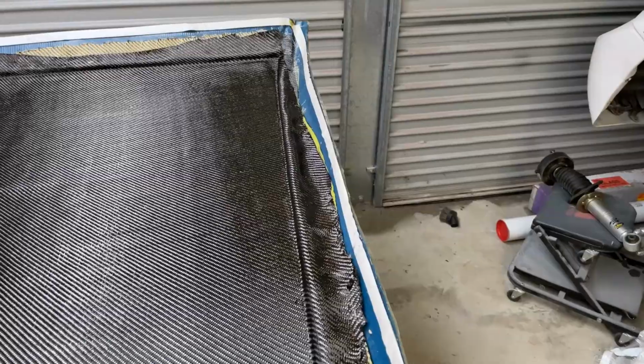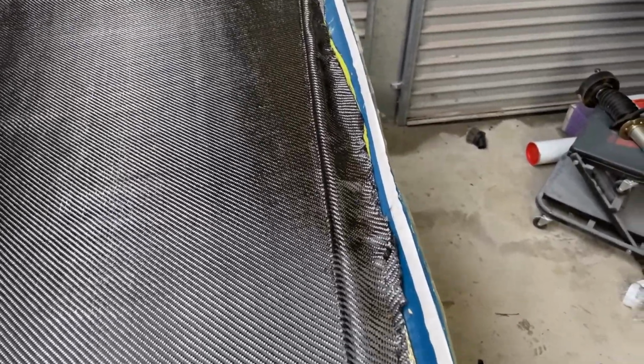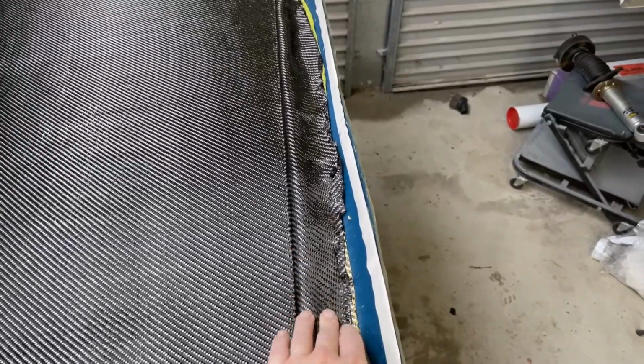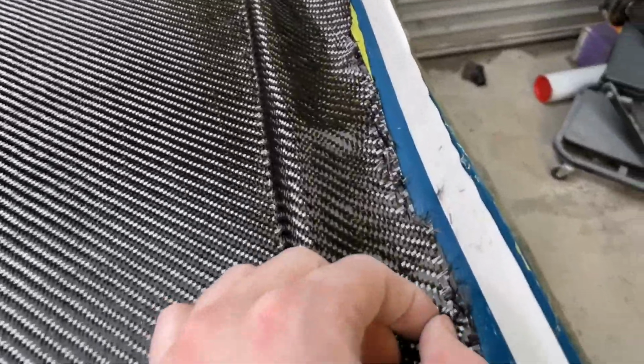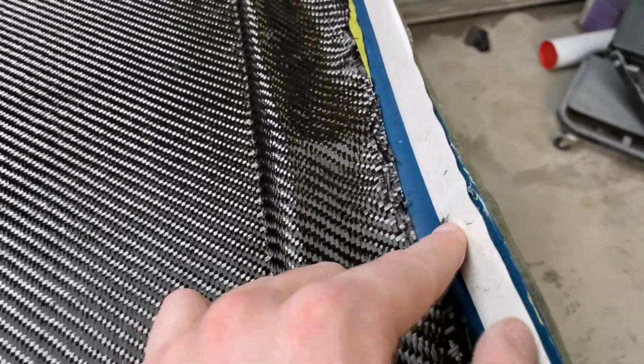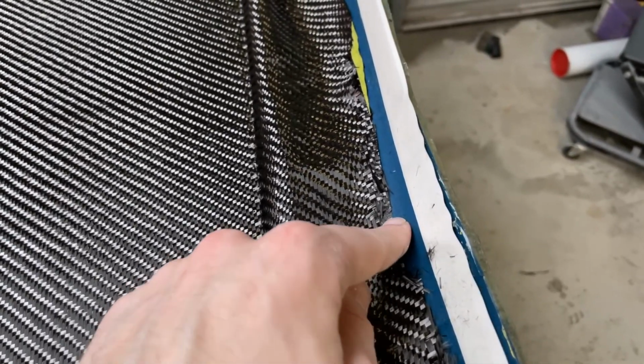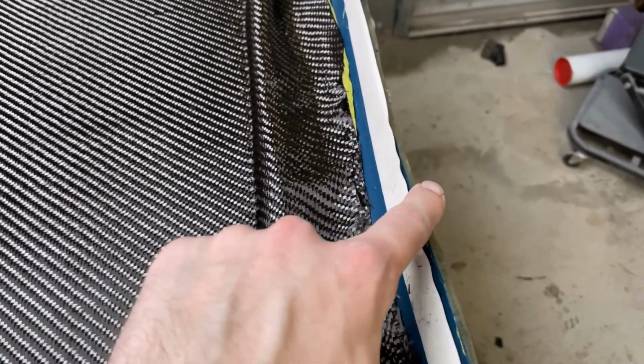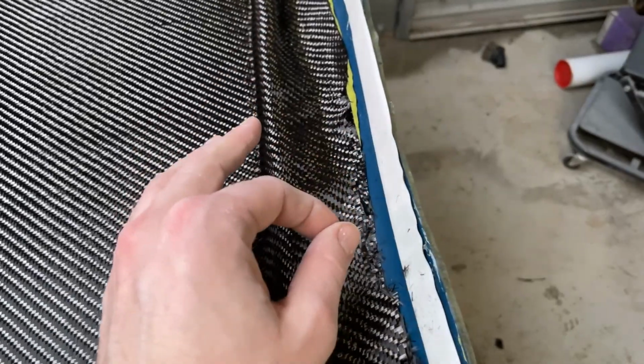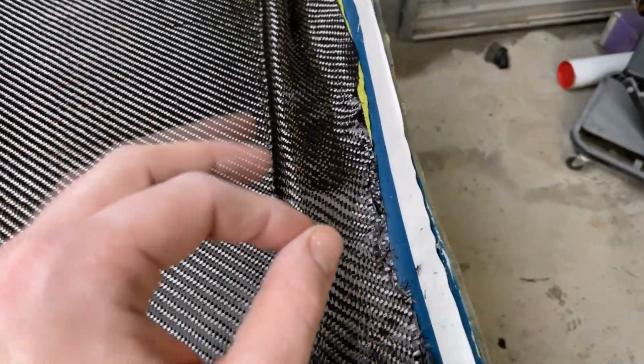So one of the most difficult things to get right with vacuum resin infusion moulding is actually getting a good vacuum on your part. Just any one of these little tiny strands, if that makes a bridge from inside the mold to the outside, that can cause a vacuum leak. And when you're trying to trace down just one little tiny, almost invisible strand of carbon fibre to find a vacuum leak, it is just about impossible.